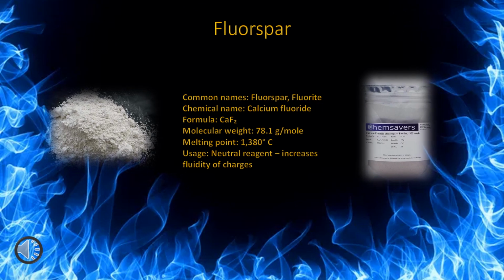Fluorspar is a neutral flux, but it has the ability to increase the fluidity of the charge, making it less viscous. If your sample contains more than 1% aluminum, this reagent is used. It has been also found to be useful in the slagging of ores that contain black sand, magnetite, and calcium phosphate. Calcium phosphate is also known as bone ash.